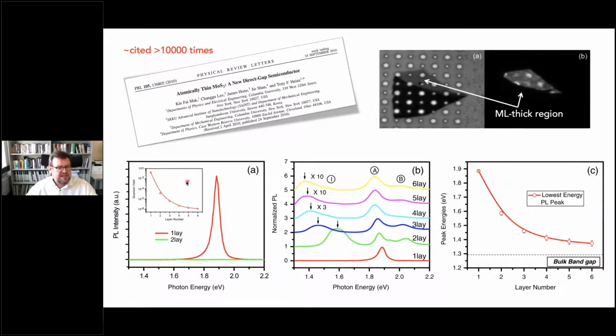But what it shows is photoluminescence arising from a monolayer of such a crystal. You see it's very, very bright. And also a bilayer of such a crystal, where suddenly the luminescence just disappears. There you see a similar type of picture. So this is luminescence recorded with a more patient person, so over long integration times, looking at what happens at the position of the luminescence from the band gap.